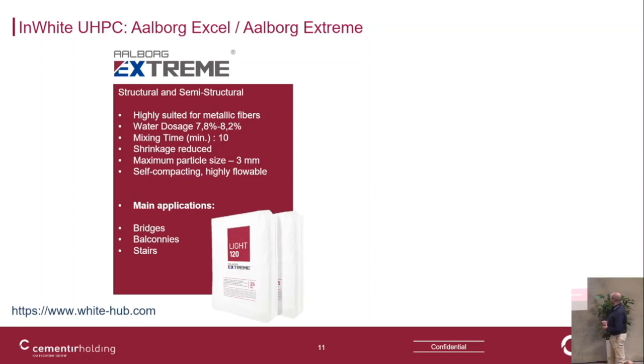The water dosage is 7.8, 8.2%. Let's say on one bag of 25 kilo, that means you have to add around 2 liters of water. It's also a shrinkage reducing mortar, and here we have a maximum particle size of 3 millimeter.